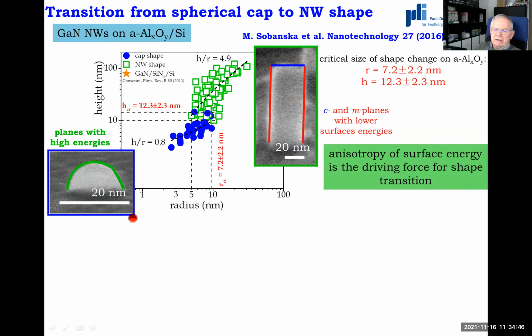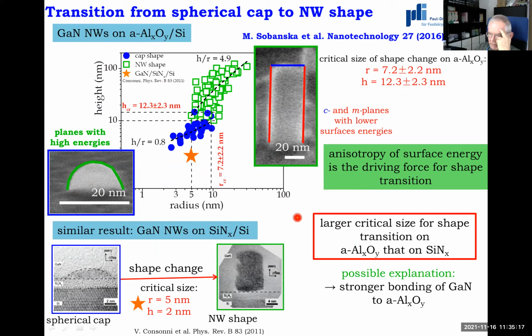We have studied this effect more precisely by measuring, on the same wafer, the diameters and heights of cup-shaped islands, these blue points, and nanowires, which are the green points. And you see that there is some specific dimension of the island when this shape transition takes place. This is explained in such a way that when the island has such a shape, surface energy is high because it contains many high index planes. So at some moment it's better for the system to transform into a nanowire shape, because then the total surface energy is lower. The driving force for this transition is anisotropy of surface energy. The same thing was earlier observed for growth on silicon nitride by Consonni. The only difference that we observed is a different critical size of the island when this shape transition takes place.